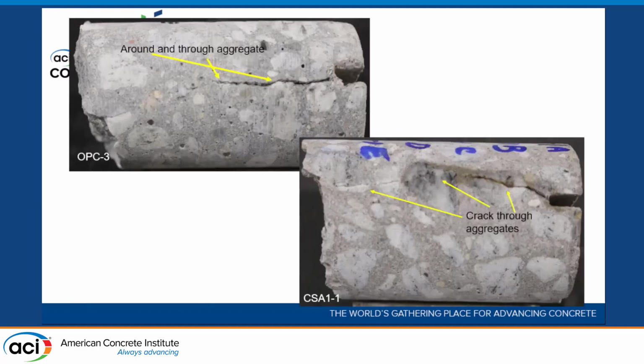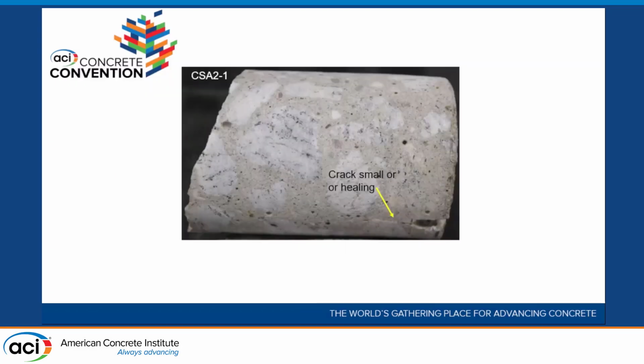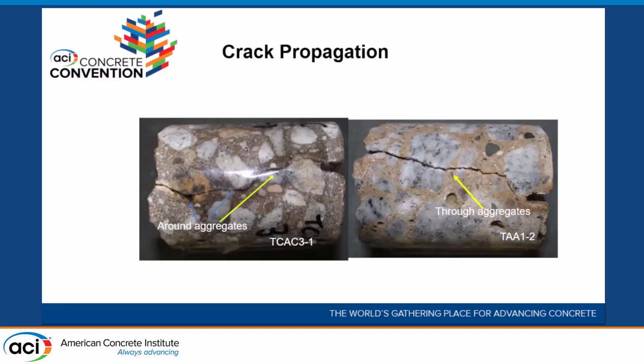So let's see. Looking at the types of, you get an idea how we cracked it. These samples were cracked in flexure. Oh, real quick, so you can see here we put a hole, and then we put them in flexure. You can see the cracks forming. And I guess you'll just have to look at the paper on the website to see more of it. The interesting thing is the CSA2 appeared to actually seal the crack a little bit over time, which was an interesting phenomenon. And there's our calcium aluminate cement. You can see how that one compared to the other ones is just falling apart.